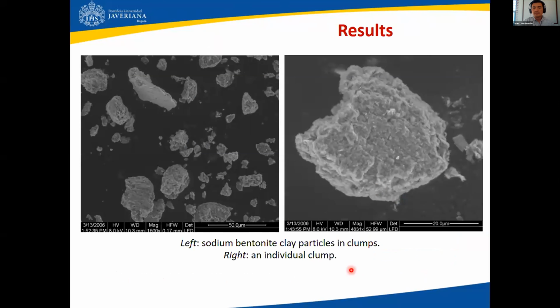So results. What you're looking at here, on the left, well, actually in both photos, is what you can see when you get bentonite from a commercial provider. What you don't see are individual particles. What you typically see are aggregations of bentonite, or rather sodium bentonite, montmorillonite clay particles in what we call here clumps. So these aggregations, like you can see on the right-hand side figure, are more silt size. You can see the scale bar here of 20 micron across, and basically you cannot see the individual particles of montmorillonite. They are aggregated in this fashion.